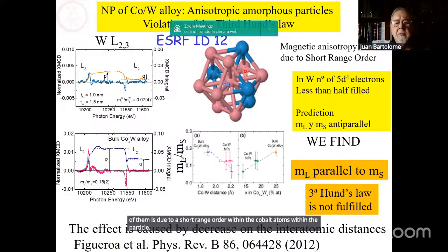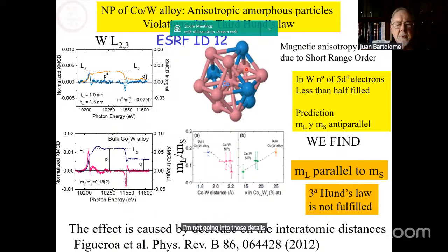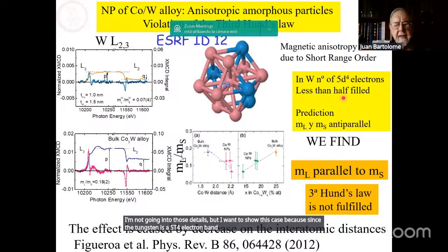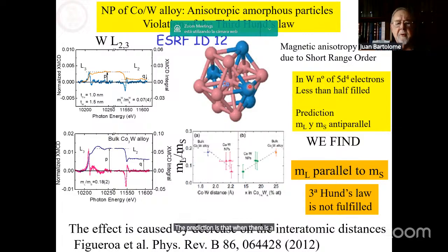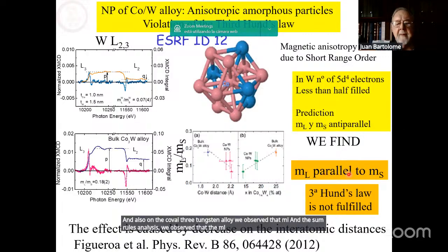I'm not going into those details, but I want to show this case because tungsten is a 5d4 electron band, so it is less than half filled. The prediction is that when it supports magnetism, ML and MS should be antiparallel. However, when we measured on our particles and also on the cobalt-tungsten alloy, through the sum rules analysis, we observed that ML is parallel to MS.